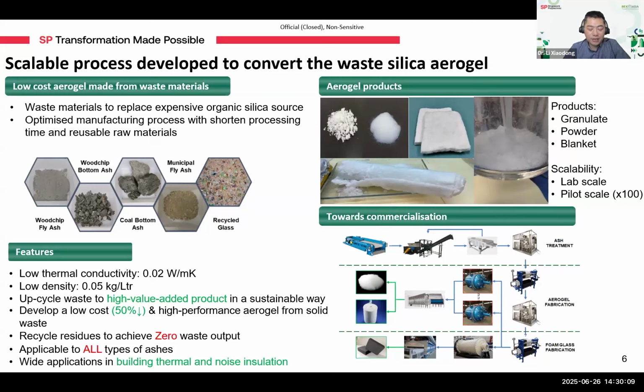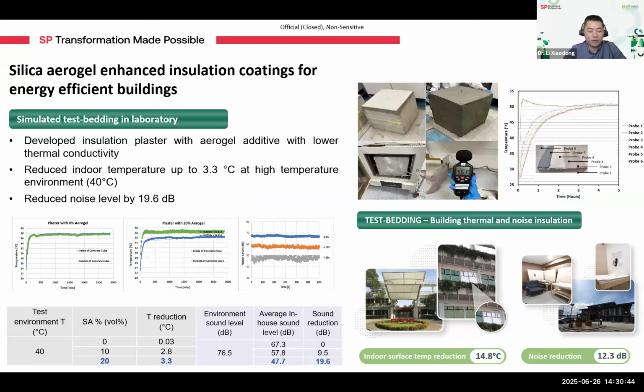Our aerogel can be processed into multiple formats: blankets for building envelope insulation, and granulates or powders that can be used as additives for different coatings. We have proven scalability by moving from beaker-scale laboratory synthesis to about a 10-liter pilot batch process, achieving a 100-fold scale-up, and this paves the way for full-scale industry production. We also designed the full industry production line. So how does it perform?